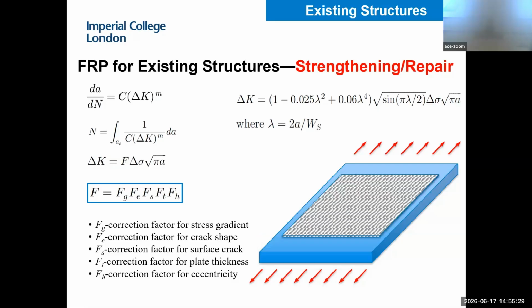However, if you cover the crack using an FRP plate, you can imagine the stress field at the crack tip will be changed, will be very different from the pure steel plate. So that means this stress intensity factor does not apply anymore. So if you don't know the stress intensity factor, you couldn't use the Paris law to do the prediction, right? So then how can we predict the fatigue life?